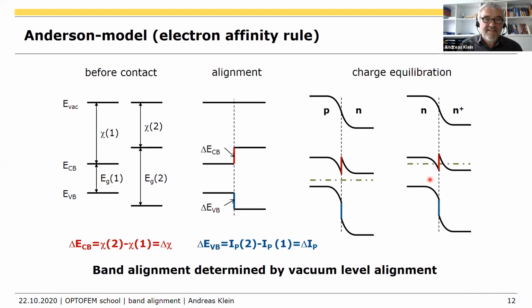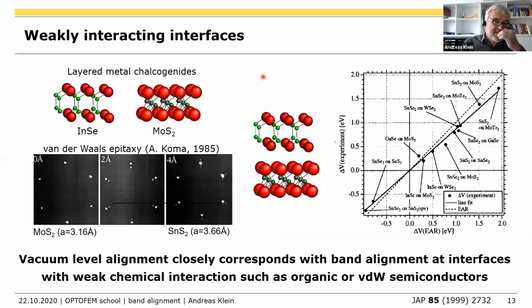Okay, so this vacuum level alignment is something you can observe in principle experimentally. And you can observe this for the layered chalcogenides, for example. You take these layered semiconductors like indium selenide, molybdenum disulfide. You can grow them easily on top of each other, regardless of any lattice mismatch. You see here some low energy electron diffraction, and you see the diffraction spots of the substrate. You see here the distance in the lattice constants between the substrate and the film. And then for a thicker film, you really can nicely grow that epitaxially.